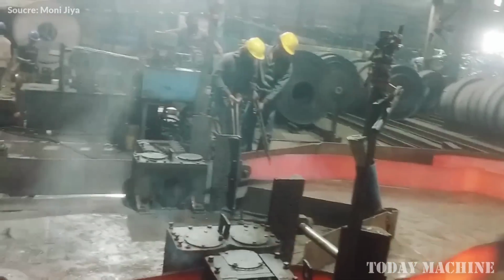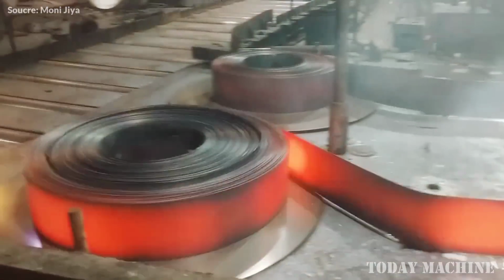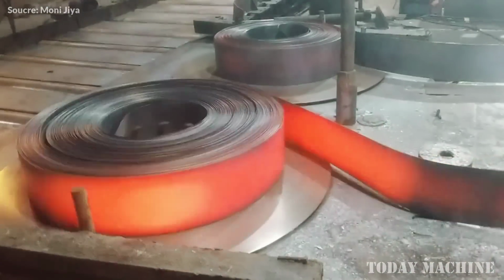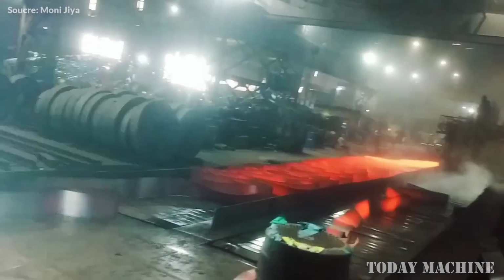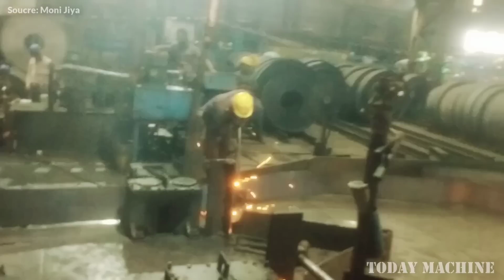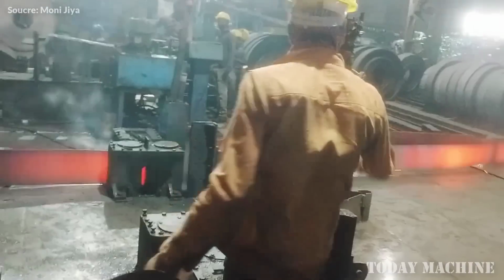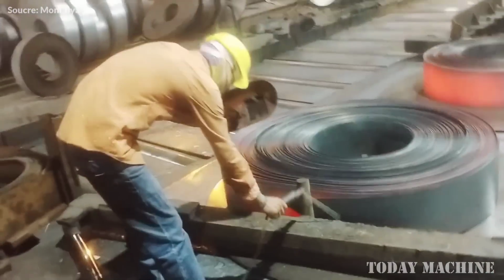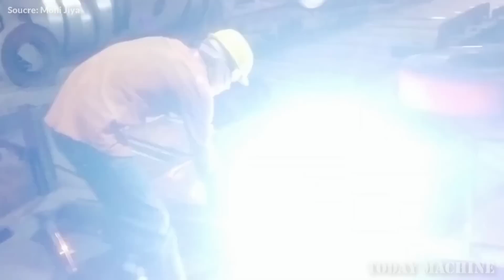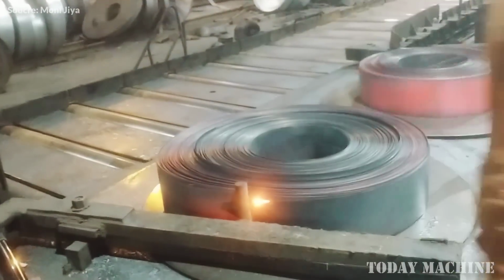After being stored, the steel slabs are transported to the hot strip mill, where they are reheated to approximately 1,200 degrees Celsius in energy-efficient furnaces. The slabs are then passed through a series of powerful rolling stands, where their thickness is reduced from 22 centimeters to between 1.25 and 13 millimeters. The hot rolled steel undergoes additional quality checks, with measurements taken for thickness, width, flatness, profile, and temperature. Once the rolling process is complete, the steel strip is cooled and coiled.